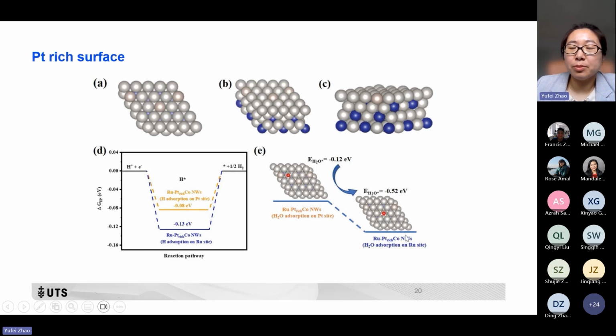But for the water absorption and desorption, we found the ruthenium has optimized the energy compared to the platinum. So for this material, the mechanism should be that the water is first absorbed on the ruthenium side, and the water dissociation also occurs on the ruthenium side, and then the generated protons can be transferred to the platinum side to produce hydrogen.